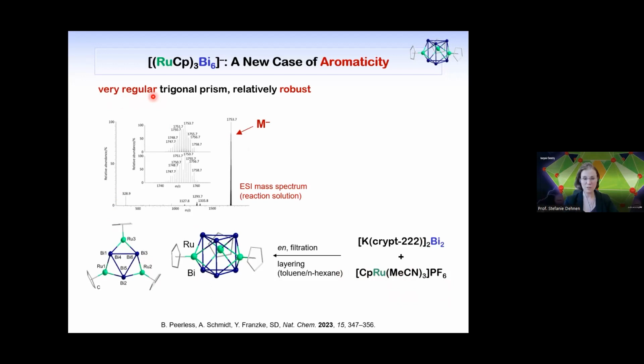And the specialty about this compound is that it's a very regular prism. And you know that symmetry is always something that sounds interesting in terms of aromaticity. And in second, it's relatively robust. So this is also a particular property of aromatic molecules, that they have a higher stability. And you see the robustness from the mass spectrometry. So this is a mass spectrum from the reaction solution, and you see just the molecular peak. So it seems to be very selectively formed and rather stable. You can transfer it into the gas phase without decomposition.